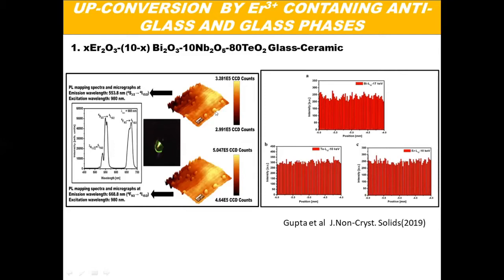We have also done micro photoluminescence spectroscopy, where we study the luminescence yield from the inclusions. You can see this picture. We can see this droplet phase and also the matrix phase. The intensity of the photoluminescence is the same from the matrix, which is glassy, and the inclusion, which is an anti-glass. And this gives you the distribution of the erbium, tellurium and bismuth ions along a line. So we take a line scan, and the distribution of the concentration of tellurium, erbium, and bismuth is the same everywhere. So the matrix and the inclusion phase are of the same composition, but their structures are very different. And their photoluminescence intensities are also found to be the same within the limits of experimental uncertainty.